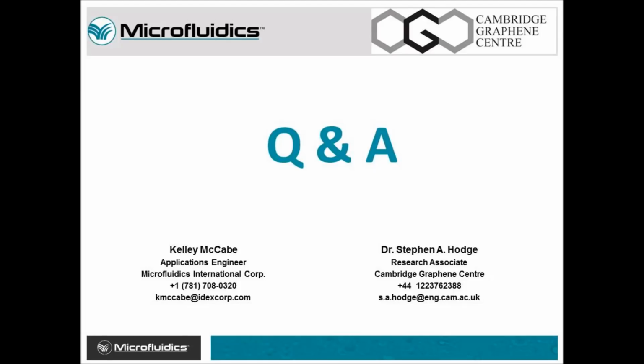I think they're asking about the actual chambers themselves, and from our experience, it's not necessary, just for the fact that the material only interacts with the interaction chamber for a fraction of a second, so it's a very small amount of time that it's actually in the chamber. So cooling around the chamber, we don't believe would have much of an impact. The heat exchanger would be much more efficient at cooling.